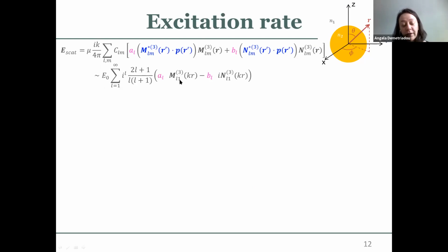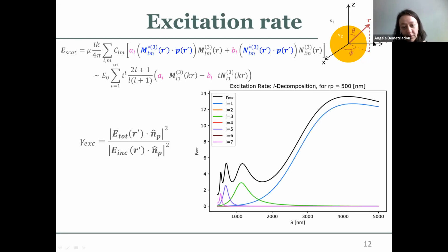And you also have a selection of the M modes, so this becomes 0 unless M is equal to 1, which is the case if you have an X polarized plane wave. If you have a different polarization, that M becomes something else. And the excitation rate is basically taking this field plus the incident one and normalizing it with the incident field, along the polarization of where you put your emitter next to the nanoparticle.